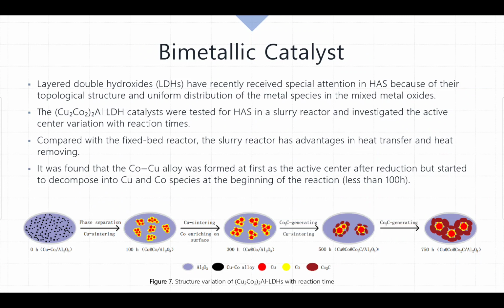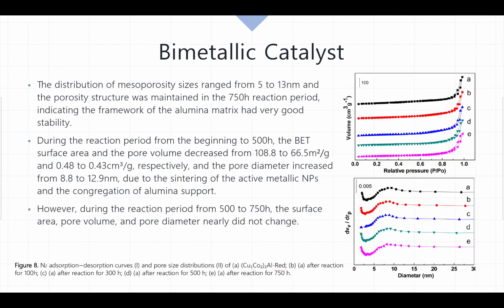After reaction for 300 hours, sintering of copper led to enlargement of copper-cobalt particles, and carbonization of cobalt resulted in the formation of cobalt carbide. At this stage, the active centers were transformed to copper-cobalt carbide. During the end of the reaction period, the copper and cobalt nanoparticles were wrapped by cobalt carbide. The higher alcohol selectivity during the whole reaction process is mainly due to the close contact of copper and cobalt species, including copper-cobalt alloy and copper-cobalt nanoparticles.